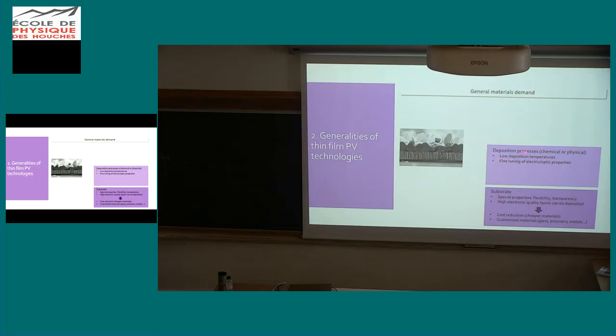Then on top of this substrate, normally we have to deposit our absorber. And the good thing about thin film photovoltaic technologies is that you can select among, I don't know, 100 different methodologies, physical or chemical. All of them have been applied and are useful for thin film deposition. And this is really very nice because depending on the nature of your material, you can choose one or another. In crystalline silicon, you have almost two ways to prepare wafers and no more. And you can have a fine tuning of the electric and optical properties with these different depositions, and also, of course, low deposition temperatures.